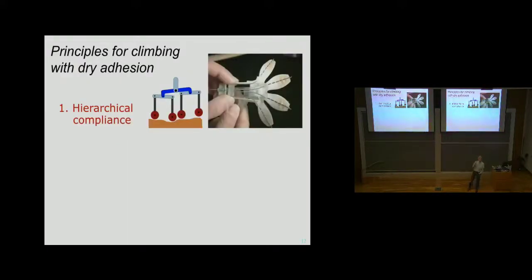All right, so let me use the Stickybot example. It's probably the most famous alumnus of our lab, to sort of make a point. When we started this work, we knew a priori that this idea of conforming intimately to surfaces was going to be important, because we're using van der Waals forces. That's this weak interaction between electrons in the outer shells of the atoms in a molecule. So you have to be within molecular distance, really, for van der Waals forces to work. Nanometers. And so therefore you really need to conform intimately to the surface you're trying to stick to. Otherwise, van der Waals forces mostly do not occur.